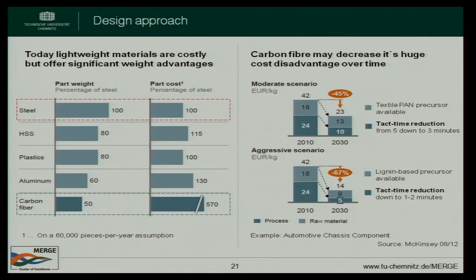I know of some research institutes in Germany looking at the development of producing carbon fiber from lignin, but at the moment it's still in research, and they don't reach the properties of the synthetic artificial fibers, and even the process is still slower. Lignin is much cheaper, of course, but with the PAN fiber, pitch fiber and the lignin fiber, lignin is still much lower in the properties. I know of two research institutes in Germany doing research on lignin fibers.